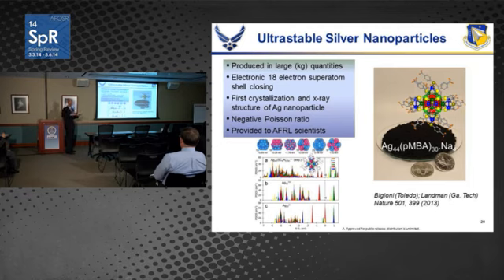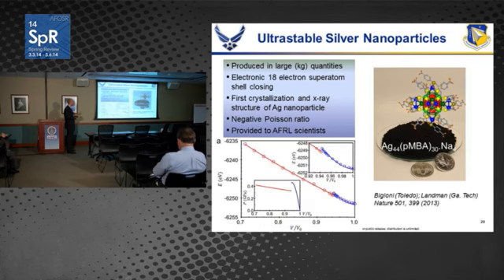So that means that in a superatom or jellium sort of model, if you've got 18 electrons available, it's a very stable shell. So it forms very stable geometric structure as well as an electronic structure. They've been able to develop the first crystallization and X-ray structure of these particles, and we've been able to provide some of these samples ahead of time to some AFRL scientists. But an interesting thing happens as this material forms the lattice that's really controlled by hydrogen bonding of these para-mercaptobenzoic acid ligands. That as you compress this material, there's some discontinuity.